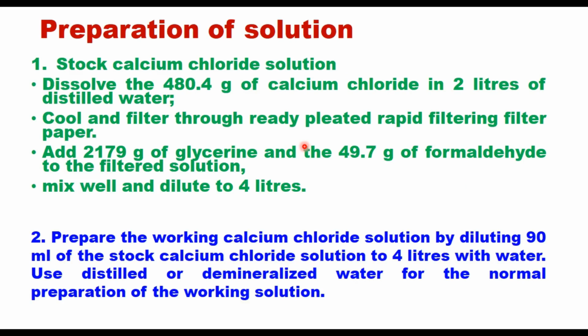For the preparation of solution, two solutions are prepared for making the test. One is stock calcium chloride solution, which is prepared by dissolving 480.4 gram of calcium chloride in 2 liters of distilled water. Then this solution is cooled and filtered through ready pleated rapid filtering filter paper. Then add 2179 grams of glycerin and 49.7 gram of formaldehyde to the filtered solution. Mix it well and dilute to 4 liters. Now this is the stock calcium chloride solution.